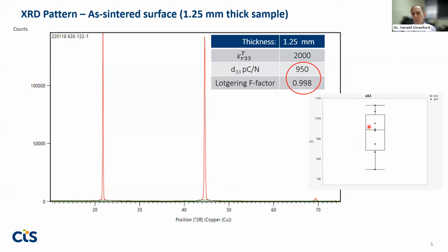The average is about 950, but on various samples, all from basically the same tape and the same layup that we were working with, centered at different times, the values range from about 750 up to 1075. So this was very encouraging.